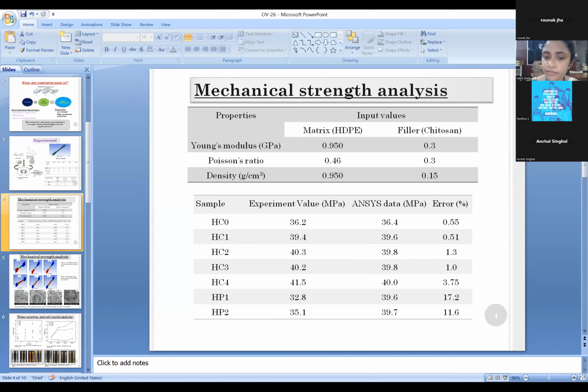Ma'am, here I have compared the tensile strength values of the experiment with the finite element analysis values. It shows how close the values of my experimental data are to the ANSYS values. When we are doing finite element analysis, we are assuming that maximum interaction is taking place between the filler and the matrix. But here it is showing an error percentage of 17.2. It shows that the interaction between the filler and the matrix is not good, and a fine homogeneous mixing has not taken place in the HP1 system. So that is the error percentage. It is showing that better interaction is not occurring when I am adding 2.58% of palm oil to the HP1 system.